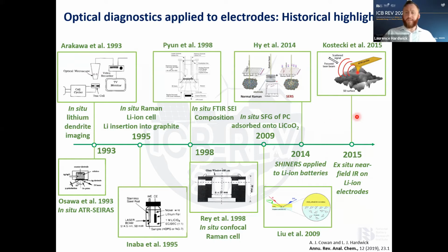And the final example I want to just highlight was in 2015, where near field infrared was demonstrated on lithium-ion electrodes. And what's really nice about that is that we were able to see the granularity of the SEI, as the near field allows us to approach a 50 nanometer spatial resolution, so we really get very detailed and very local information on the chemical nature of the SEI. So these are some of the important developments I wish to highlight.